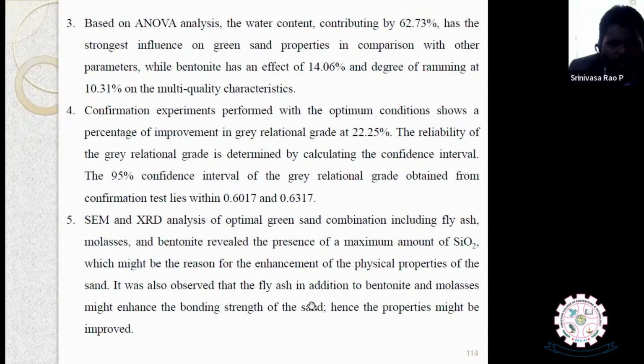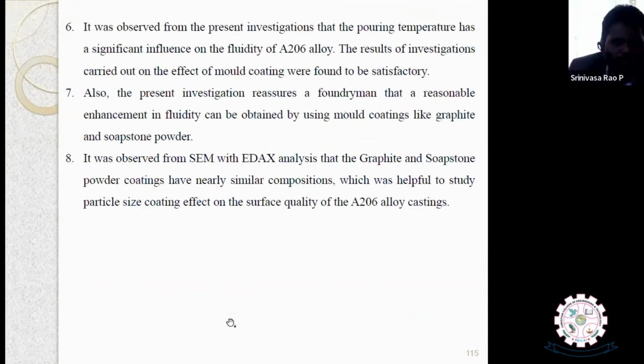Also, by using fly ash, bentonite and molasses, the bonding strength of the sand will be increased, hence the properties are improved. Okay. So pouring temperature plays the main role, and soapstone powder coating also plays a main role in improving the fluidity. The present investigation found that a reasonable enhancement of fluidity can be obtained by using mold coatings like graphite.